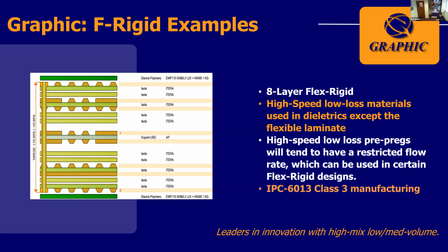When we are working with FR4 materials, you do get a very good flow in the resin. But when you move up to these higher speed materials, you do end up getting a bit of a restricted flow rate, which is ideal potentially for flex rigids. So in this particular design, we've used those low-loss, high-speed materials throughout the entire construction, except for obviously the flexible laminate, and then produced the flex rigid with those materials. It's not always compatible, these materials, for all flex rigids. Please do always check with your fabricator that they are happy to work with those materials in that particular construction. But it does show that things can progress when running higher speeds on flex rigids.